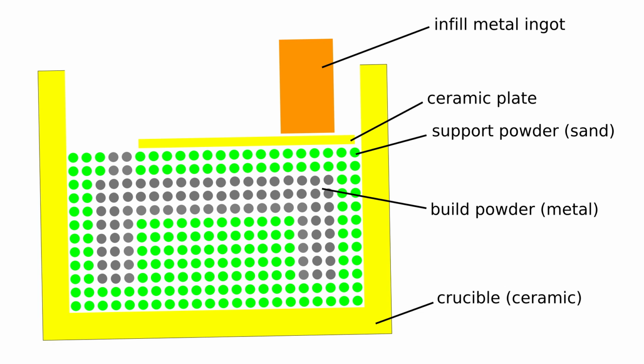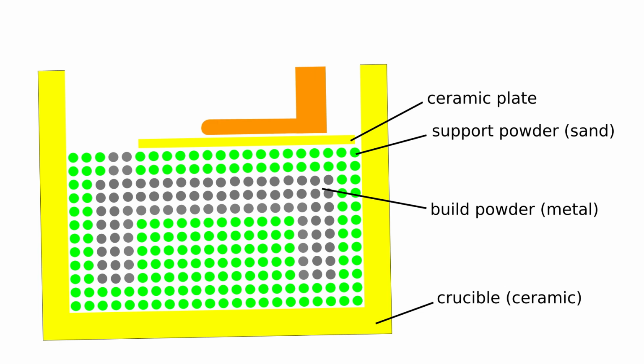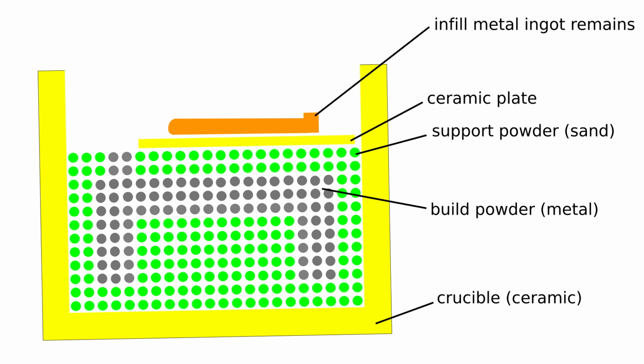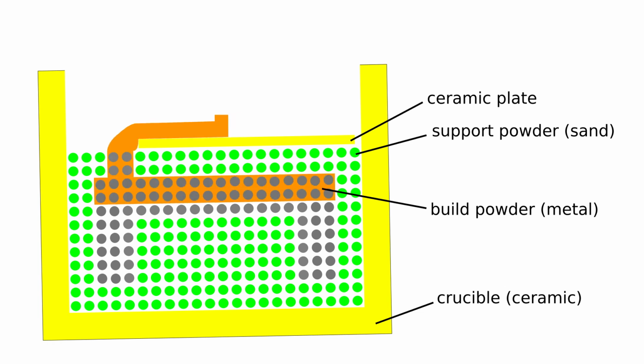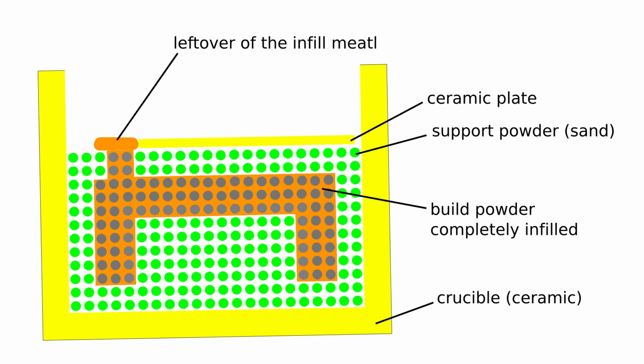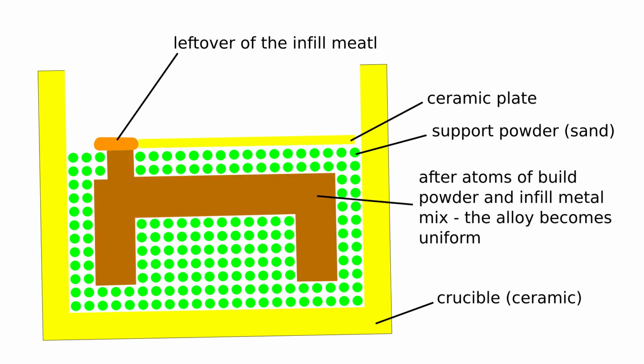When the ingot starts melting, the puddle of molten metal starts forming near it. Despite the tilt, the puddle doesn't separate from the ingot because of the surface tension. So here our ingot acts as an anchor. When the ingot has melted almost completely, the puddle of the molten infill will run downhill. When it reaches the collector, it soaks the powder rapidly. Because the infill time is so short, the atoms don't have much time to diffuse, so we obtain an even distribution and a uniform alloy.